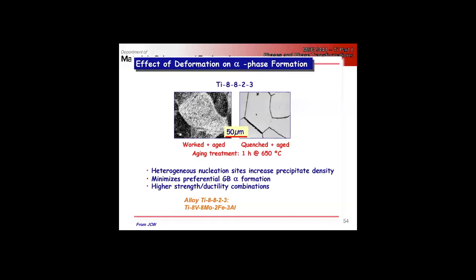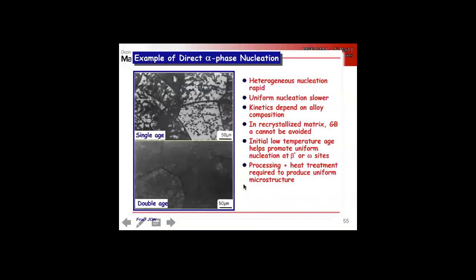All right, this is nucleation at dislocations. Notice in the quenched and aged case, we're starting to nucleate grain boundary alpha. So heterogeneous nucleation is going to be much more rapid than uniform nucleation. If we're fully recrystallized and recovered, so if we have a well annealed structure, we're not going to be able to avoid grain boundary alpha.